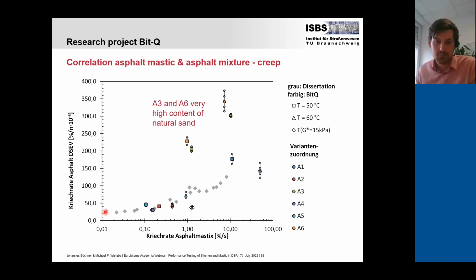So all the other materials which we see here were created with crushed sand. So here's the limitation of this correlation, that we have to use a similar type of sand, because the sand affects this high temperature performance of the asphalt to a huge extent.